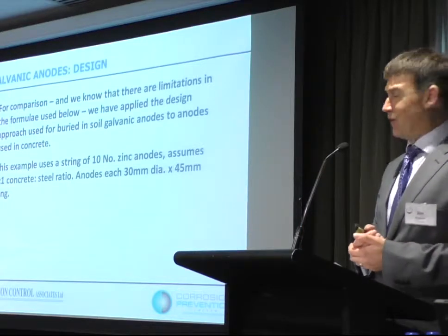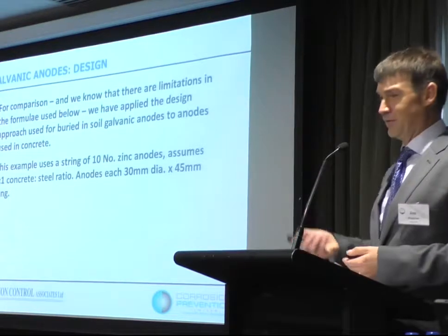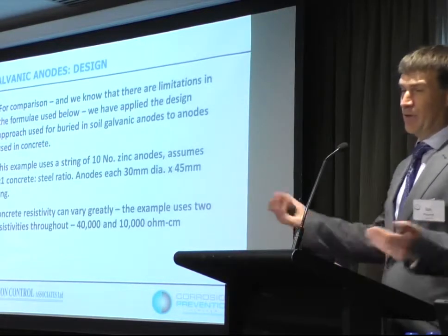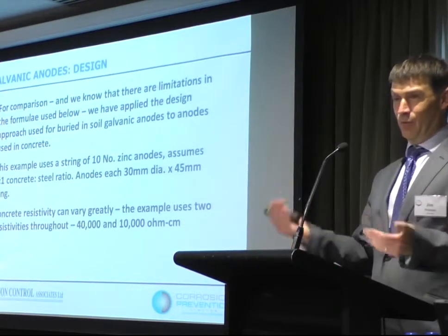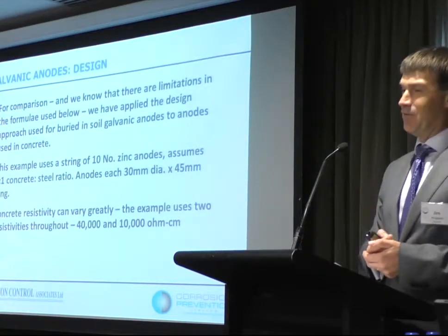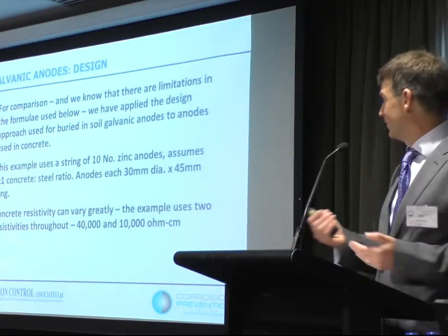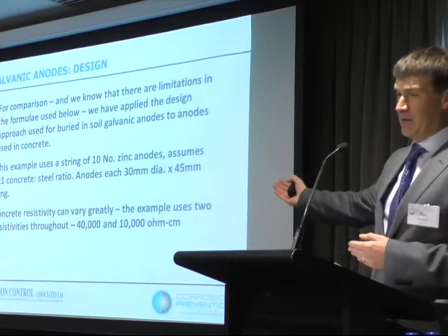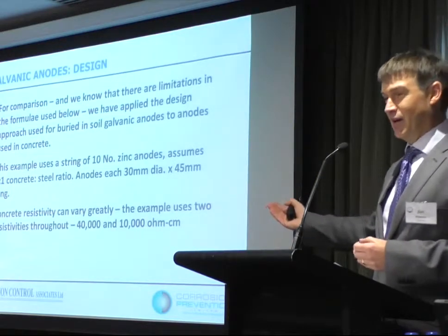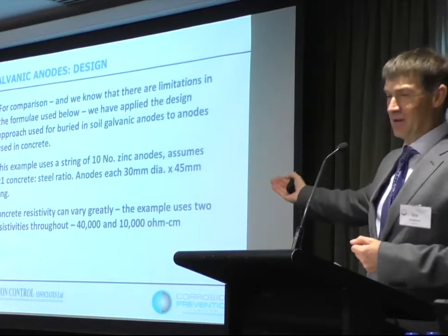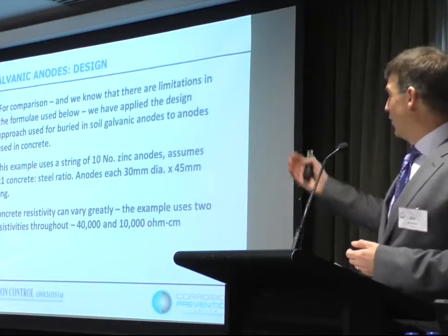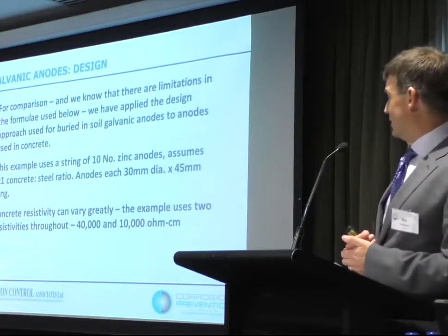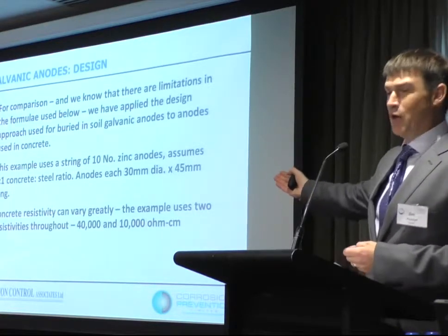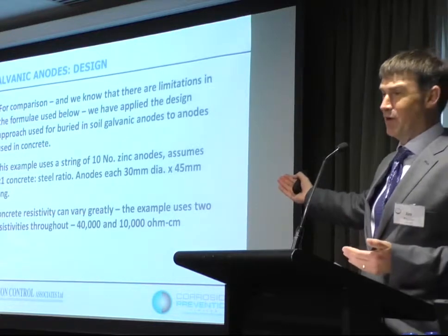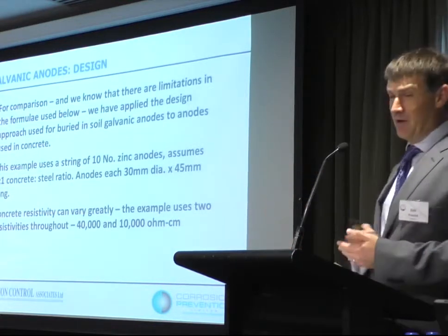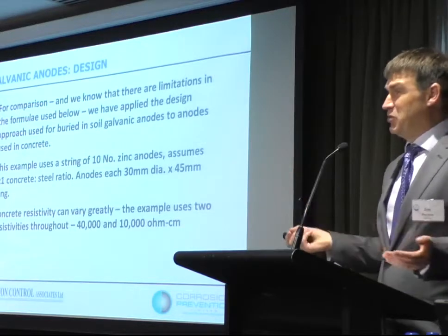Let's just crib one off a manufacturer's data sheet. Let's say they're 30mm diameter by 45mm long anodes. We know we need the concrete resistivity in order to start working out these equations. And we know resistivity of concrete can vary a great deal across a structure even. So we've picked two values. We picked 40,000 ohm centimeters because we've got field data of corroding reinforcement, and adjacent to it, that's the resistivity of the concrete. So I know I can get corroding reinforcement at that resistivity. But I know at lower resistivities, if my structure's partially submerged or immersed, my resistivity might be a lot lower. So we picked a lower value as well, just to see what happened.